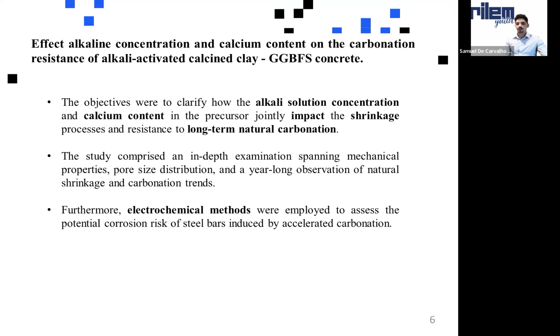So on this study, you comprise the examination of also the mechanical properties, the pore size distribution, and 1 year observation of natural carbonation trends. Further, you used some electrochemical tests to assess the potential corrosion risk of the steel bar induced by the accelerated carbonation.